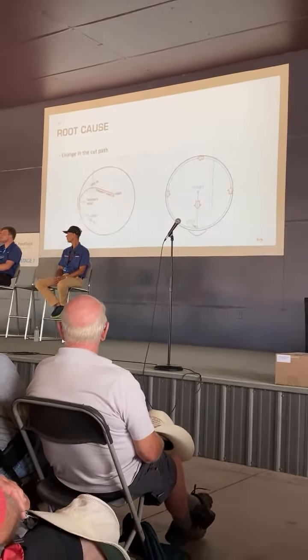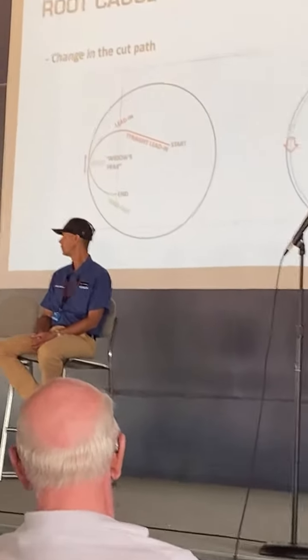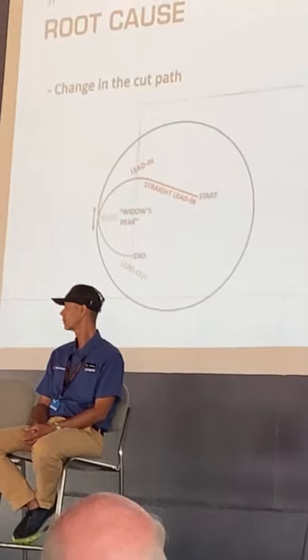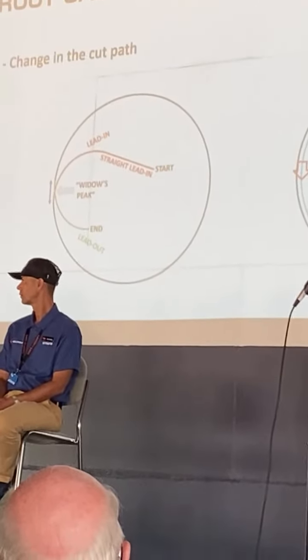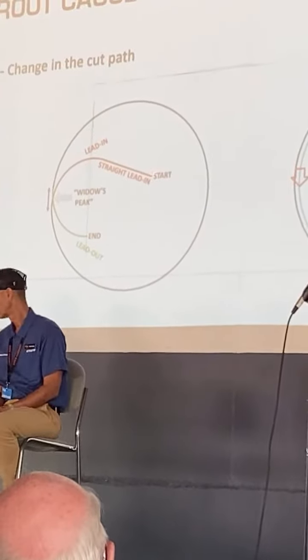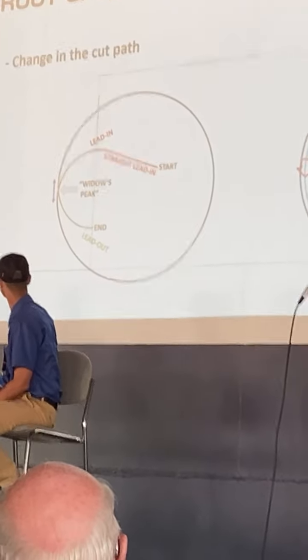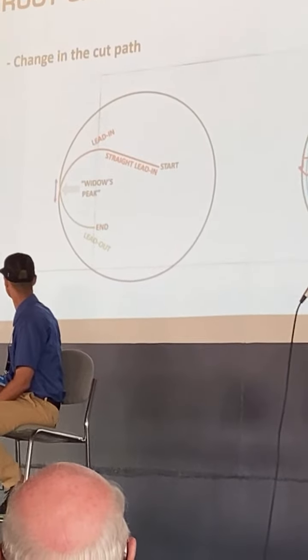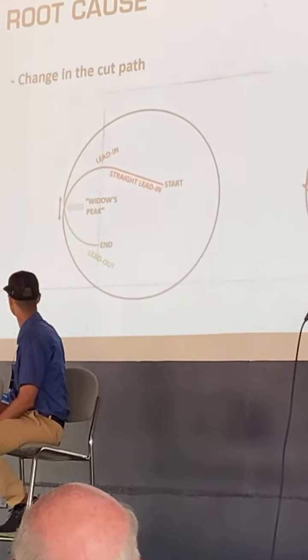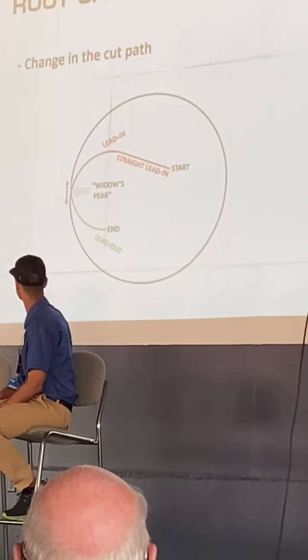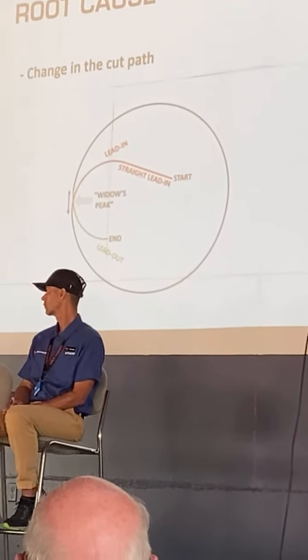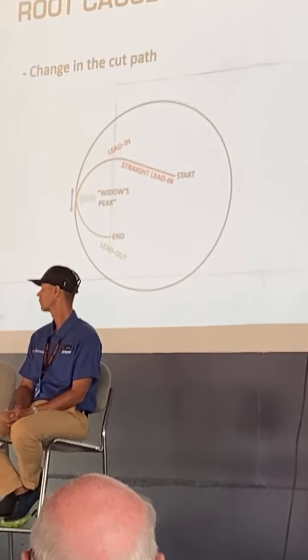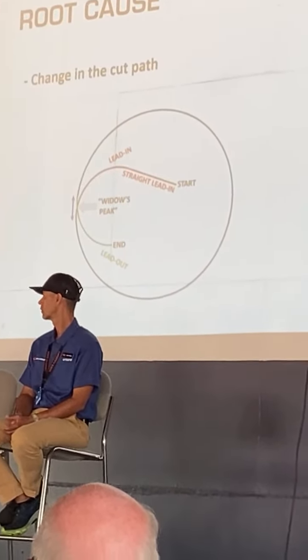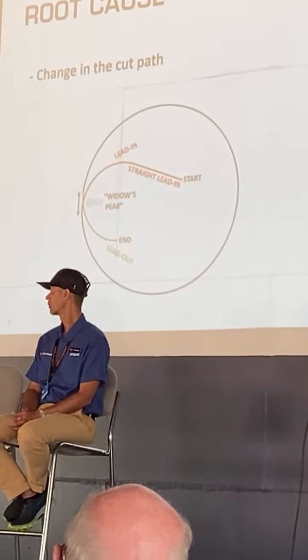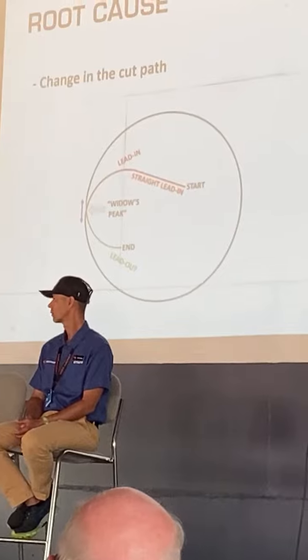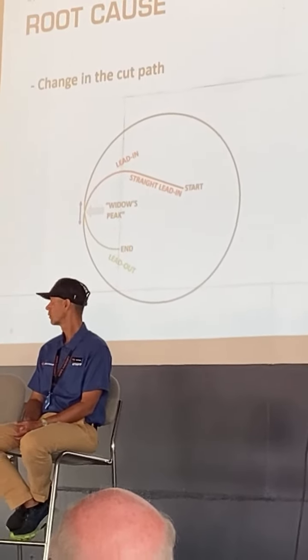The root cause of the problem, the ways that the holes are specified to be cut, if you start in the center of the hole here and pierce the hole there, come around with the laser all the way around and in there, there's only a very small heat affected zone along the edge. And the advantage of a fiber laser, and why we looked into a fiber laser, is that it passes very quickly through the part and has a lot more power than the old CO2 lasers, where historically parts were not laser cut in the industry. And leaves a very small heat affected zone.